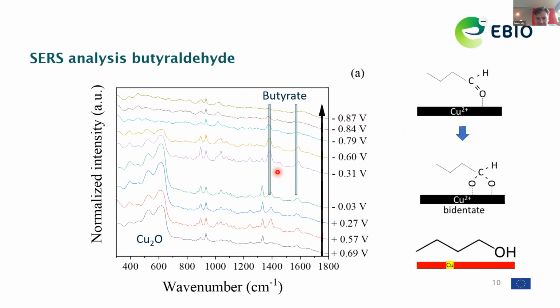So in summary, we see at some potentials strongly adsorbed intermediates of the reactant on the surface, which becomes partly oxidized by the fact that we do have an oxidized copper surface. But in the process conditions, there's very little adsorbed species, as you can see from the limited intensity of the Raman bands in the spectrum during the reaction.